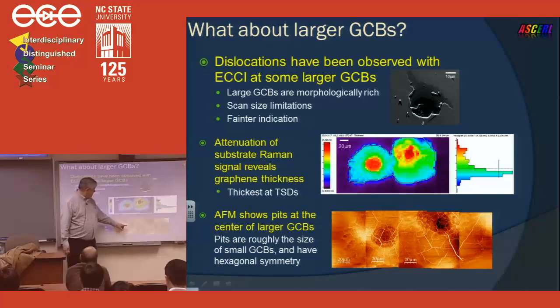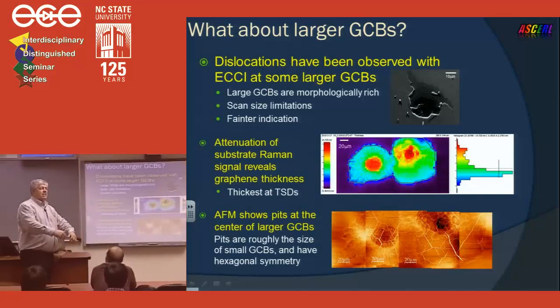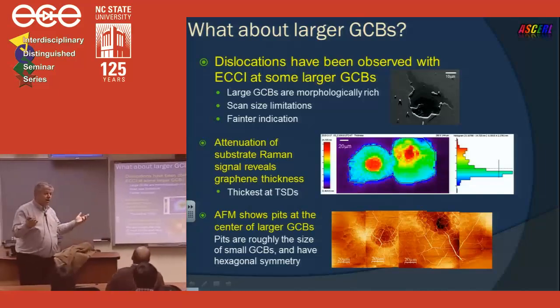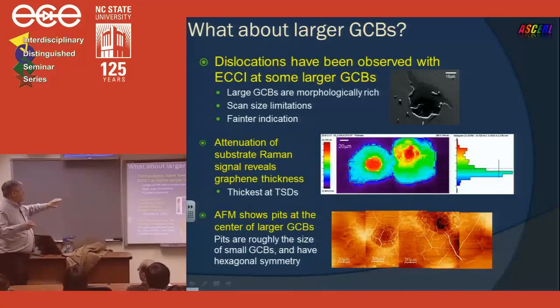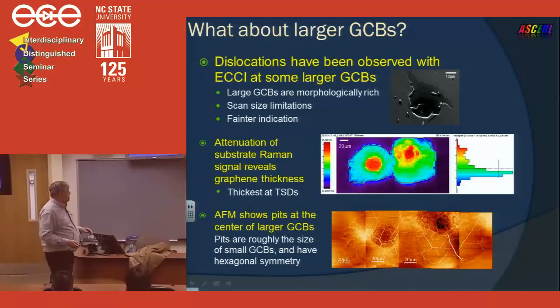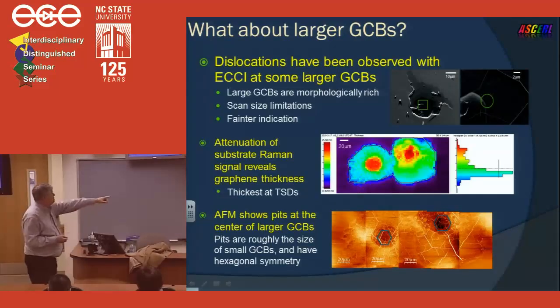Now look at the AFM images. Dark means it's low, and white means it's high. That's the way the AFM scale is set up. So for these particular graphene basins, this region here and this region here are low. They're below the surface. And the white ridges are high. They're above. So where the graphene is thickest is the area that is also the lowest, and that's because that's where the screw dislocation is located, and it's eroding as the silicon atoms come out, and then the carbon atoms can diffuse out, so naturally the graphene will be thicker there, and you have to go out to the edges because it takes a while for the carbon atoms to diffuse out there. So this all holds together. This particular basin does have a little screw dislocation in it.